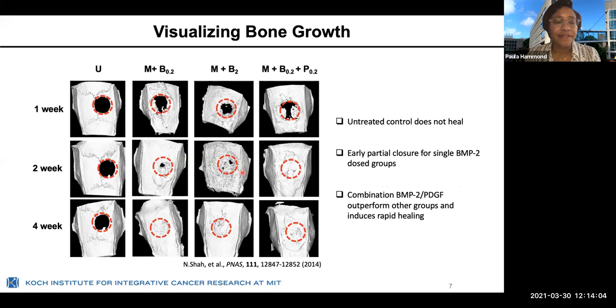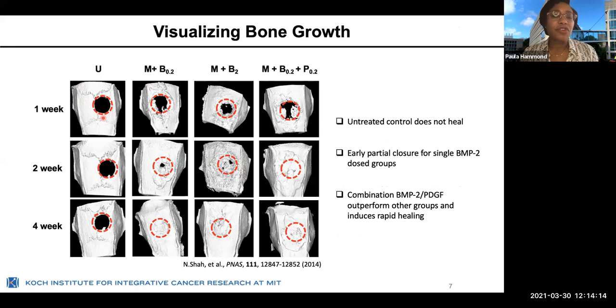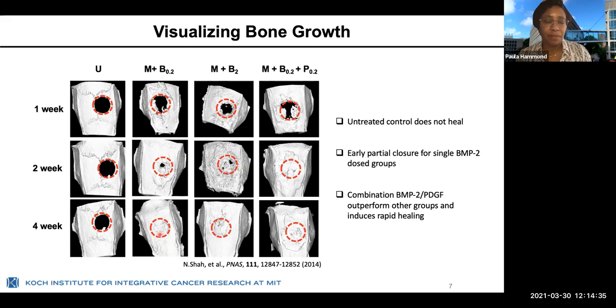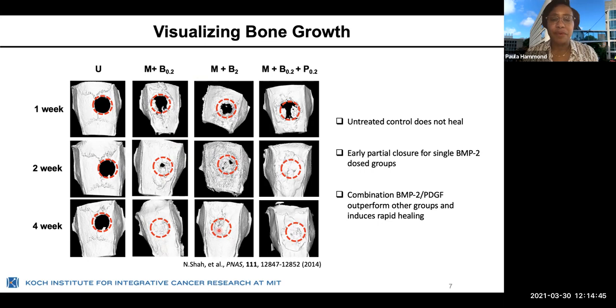We examined a rat cranial defect model — a hole in the skull. Using micro-CT, an untreated control shows no closure over four weeks. With our membrane coated with 0.2 micrograms of BMP-2, we see significant bone deposition and defect closure over four weeks. Increasing the dose to two micrograms produces excess bone formation and a visible lump on the skull. In both cases, closure takes place somewhere between the second and fourth week.